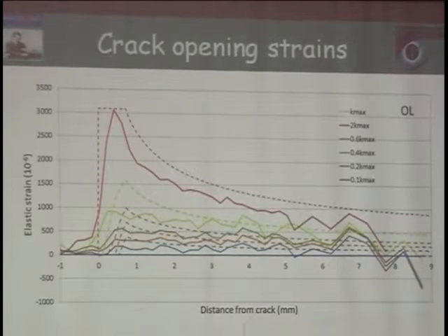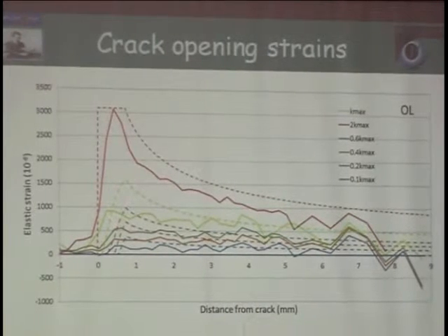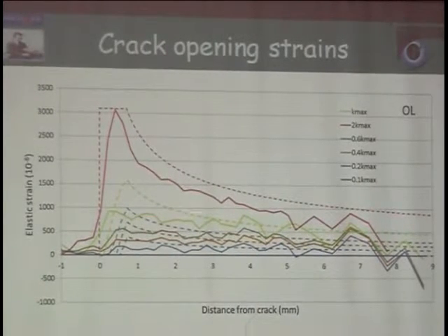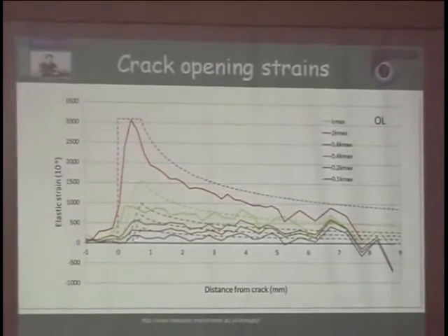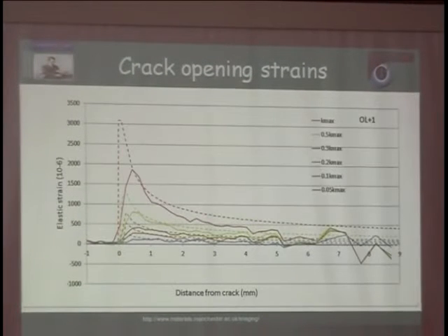As you go to the maximum load, again you can see the curves don't quite work here near the crack zone. They work further away, but they don't really work quite at the crack tip. And then after overload, you see that they work reasonably well, except right at the crack tip. So that was all in plane stress.